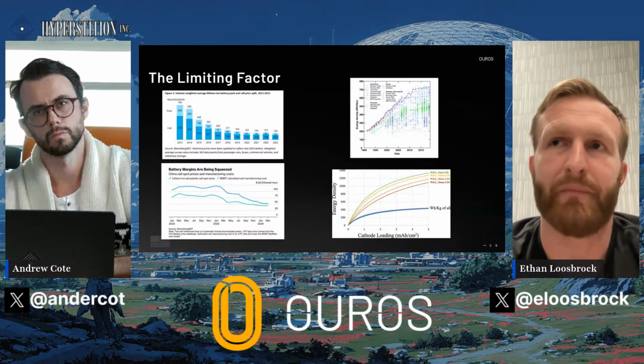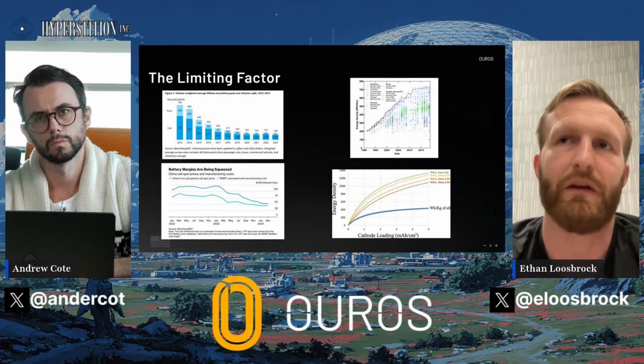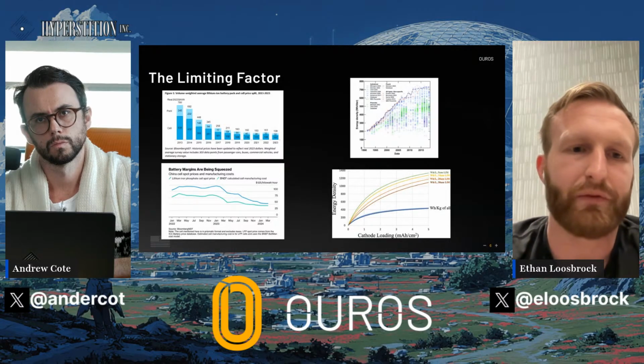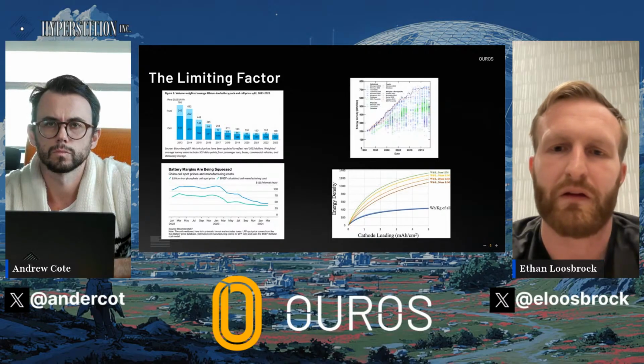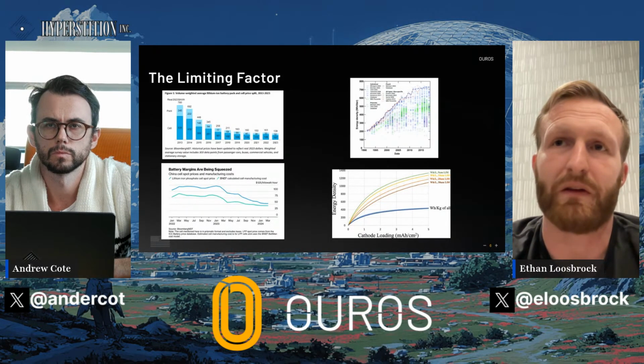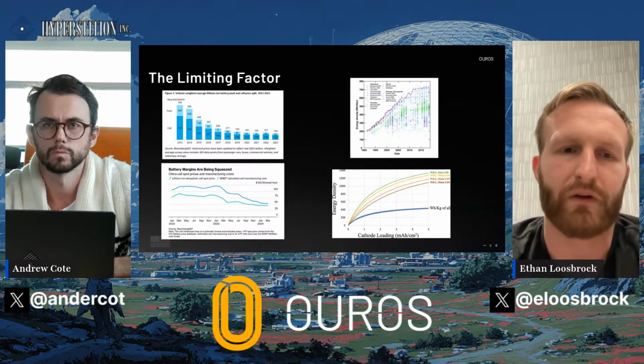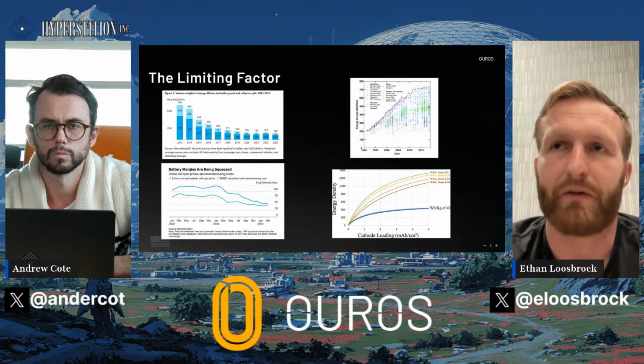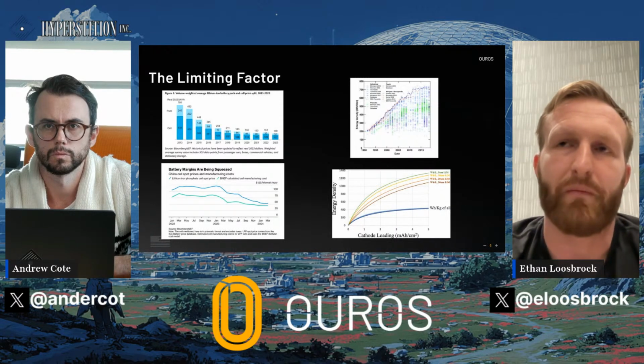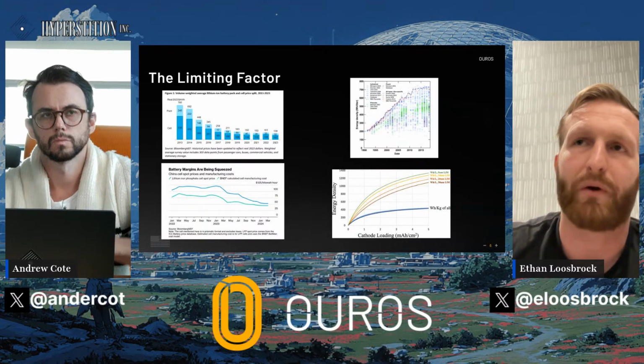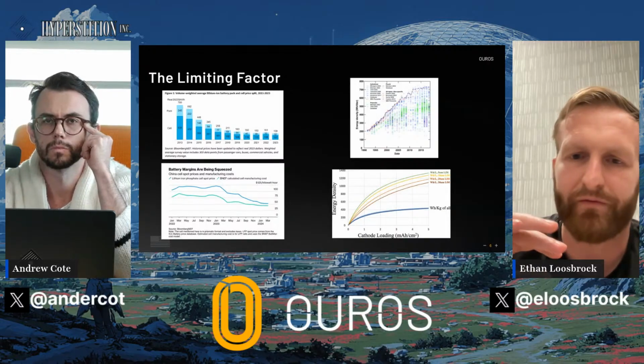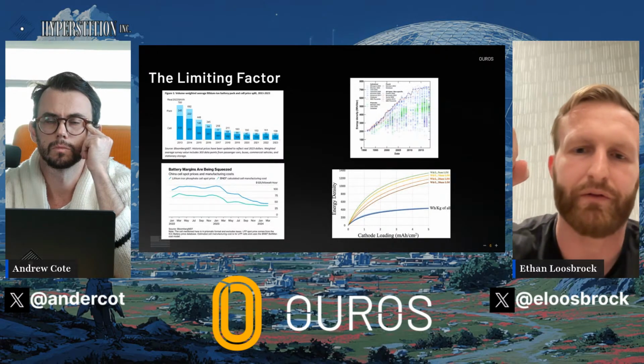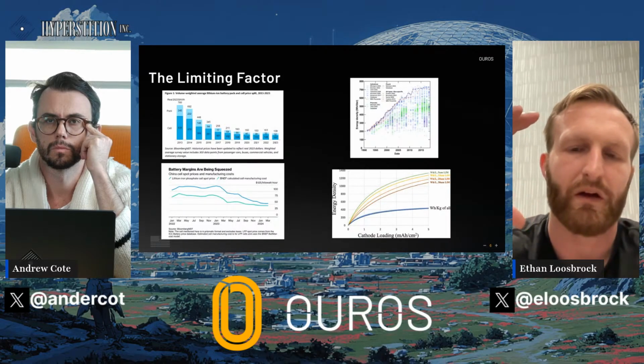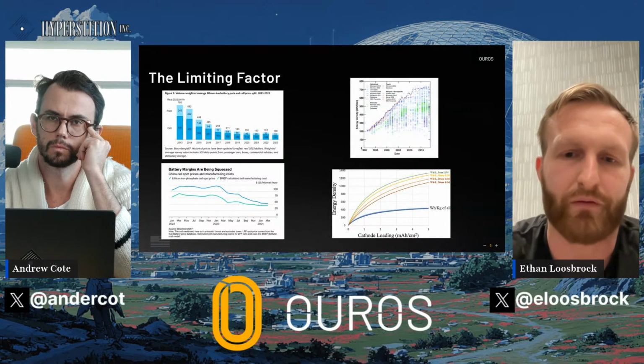So the main challenge for silicon today, though, is this: they've solved the safety more or less, and they've solved the performance, but the one remaining challenge to solve for silicon is the one that was maybe the most promising in the beginning, which was cost. The way people have solved it today is they use silane gas, in essentially a chemical vapor deposition process. They impregnate hard carbon particles with silicon metal. They vaporize silane gas, and these nano little dispersions of silicon deposit inside the pores of a carbon sphere. This solves your performance problems and your swelling problems, but it's extremely expensive.